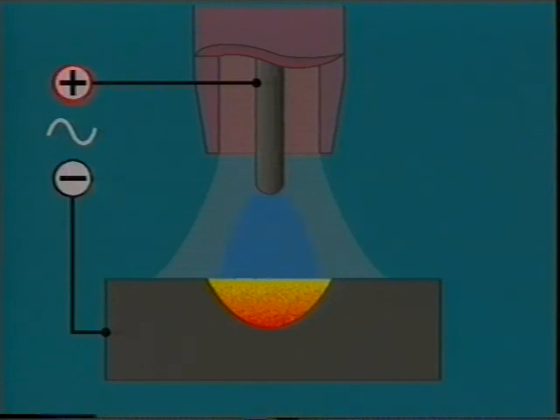In AC mode, the arc polarity changes with the frequency of the main supply. The arc is both DC electrode negative and DC electrode positive, with alternate half cycles, providing the heat to melt the workpiece and the cleaning action as the surface oxides are dispersed. This makes it an ideal process for welding aluminium, where oxides rapidly develop on the material surface. As the current is reversed, the arc is extinguished and needs to be re-established. This has presented some problems in the design of power sources due to effects which prevent the arc reigniting. Advances in AC welding power sources allow for simplified machines with improved arc characteristics and better arc reignition. Because of this, AC is now widely used for welding aluminium.